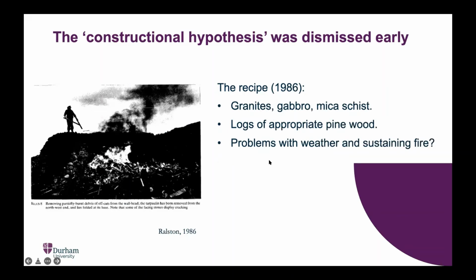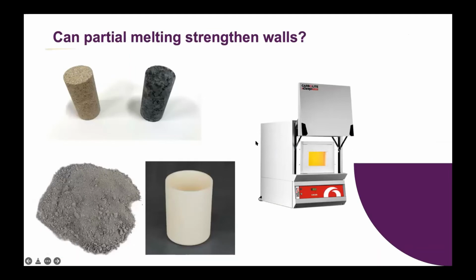These sorts of tests were then repeated in 1986. This was actually broadcast on the television as well. And this time, Ian Ralston did it correctly. He used granites and gabbros and schists. He used an appropriate type of wood, but unfortunately he had problems with the weather and wasn't able to sustain the fire for very long. And so the temperatures were much, much lower than they probably could have been. So we felt like the constructional hypothesis deserved testing some more, because we thought both of those experiments that have been performed on large-scale reconstructions of walls haven't been a good test of the hypothesis.